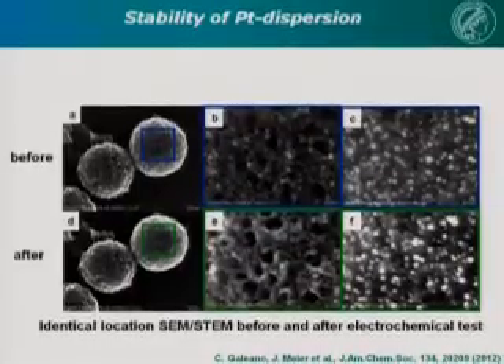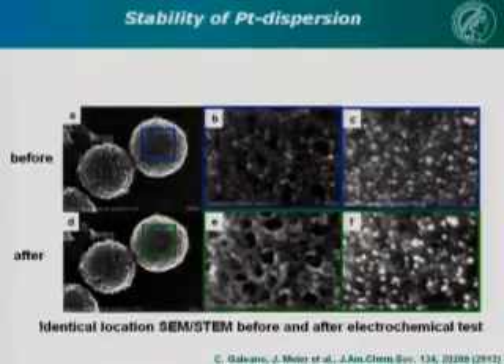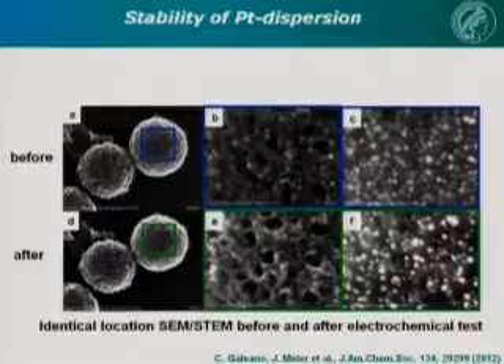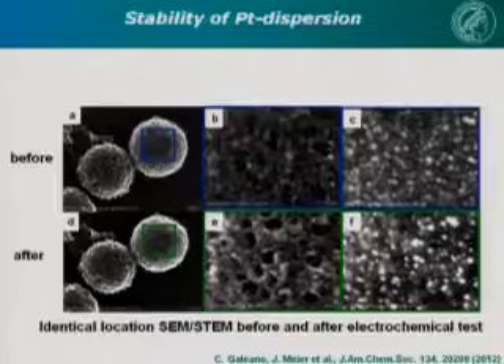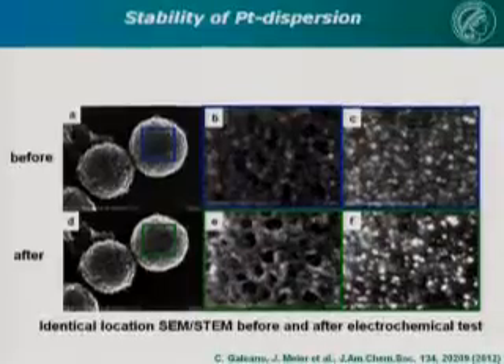And this is something we do with Josef Meier and Karl Meyerhofer in the Max Planck Institute in Düsseldorf. They have developed the so-called identical location electron microscopy. They did that for TEM, and we extended that to SEM-TEM. What you basically do, you put your catalyst on a finder grid for the electron microscope, which has coordinates on them. You analyze the catalyst. This is what is done here. So this is a place on the catalyst, analyzed with both scanning and transmission.